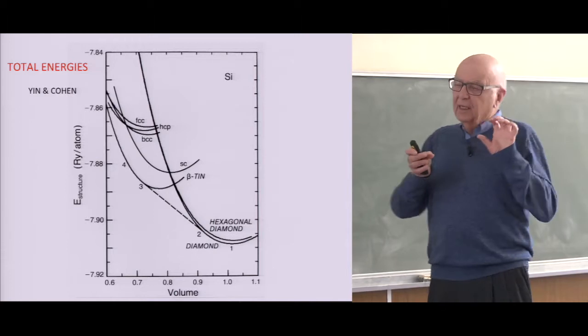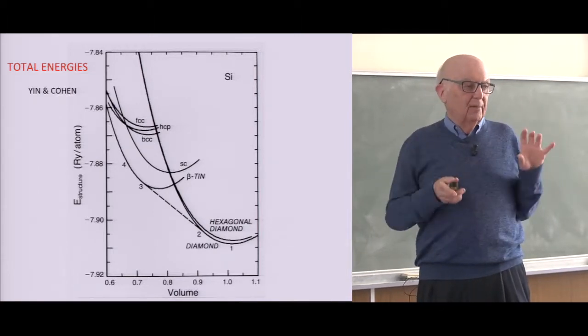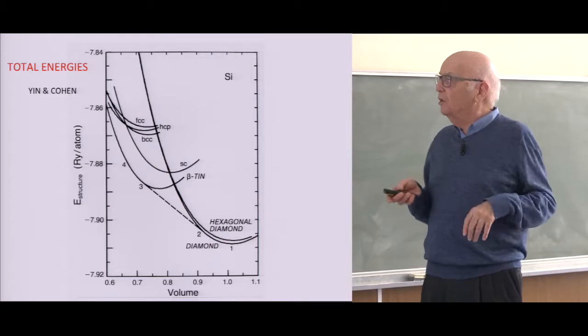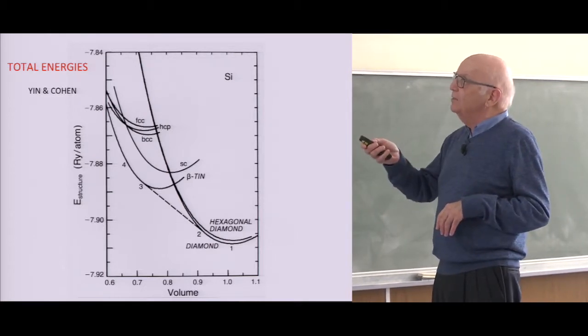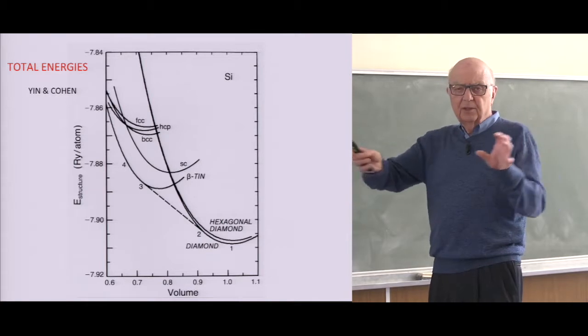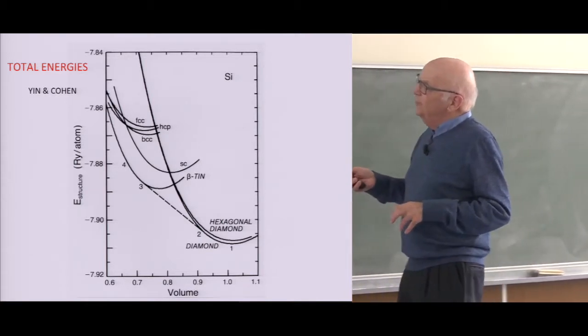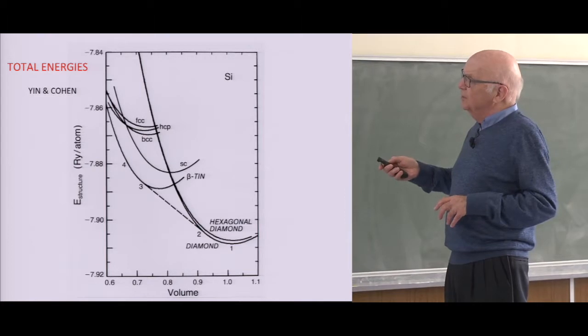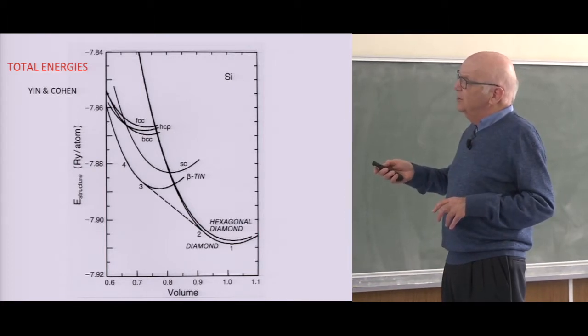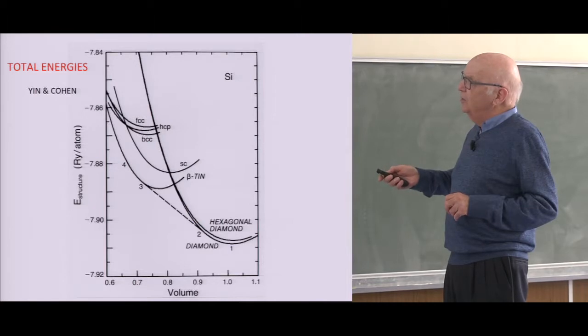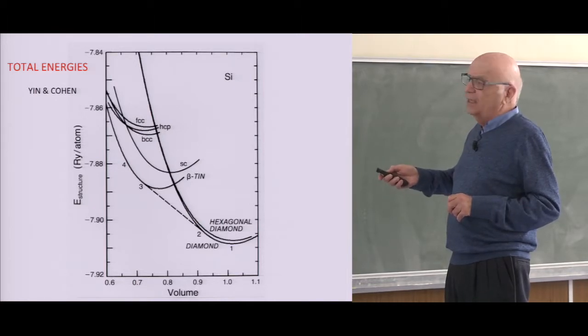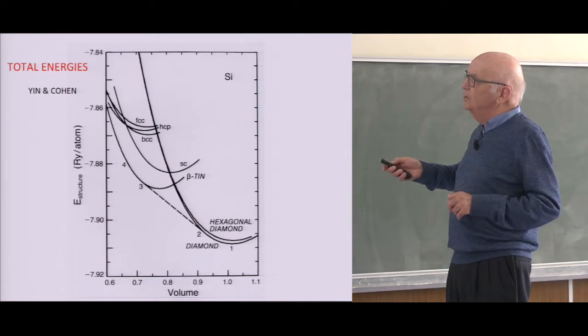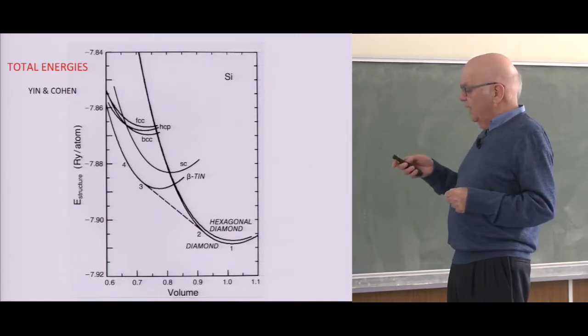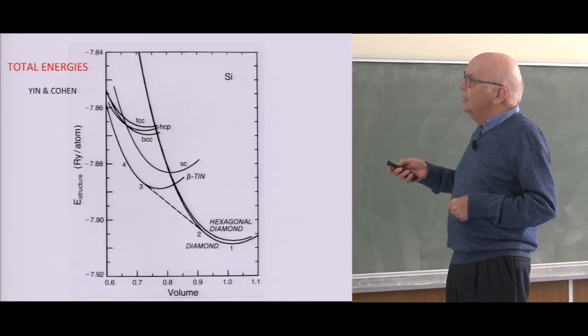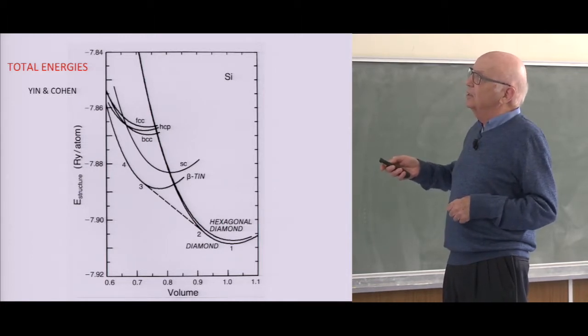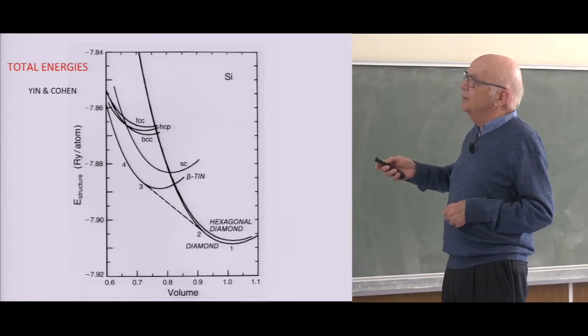If you take silicon atoms and you put them in the usual structure, diamond lattice, you add up the total energy, and you plot that total energy as a function of the volume. You just change the volume. Then for the usual silicon, which is diamond structure, you get a curve like this. This is the minimum, and this is real silicon, and you can measure this point, and that gives you the lattice constant. And the curvature gives you the compressibility. Now, if you squeeze silicon, it will go into another structure, and that's a metallic structure, beta tin.